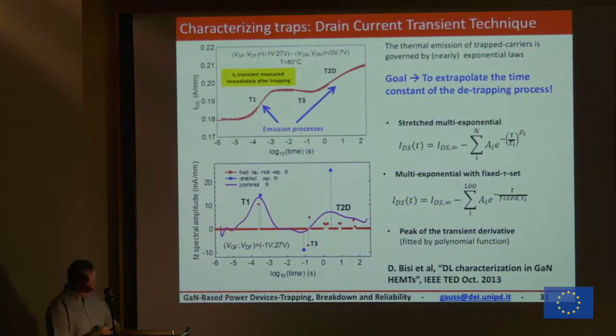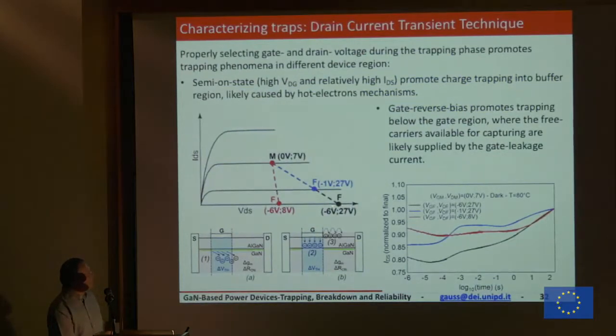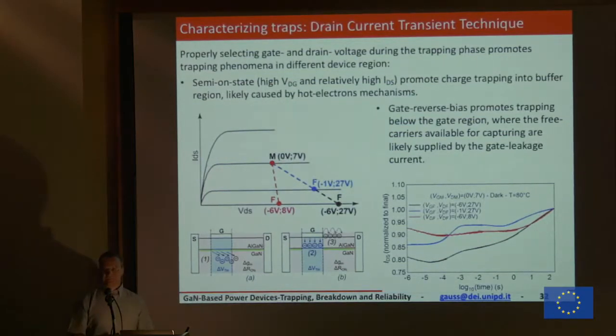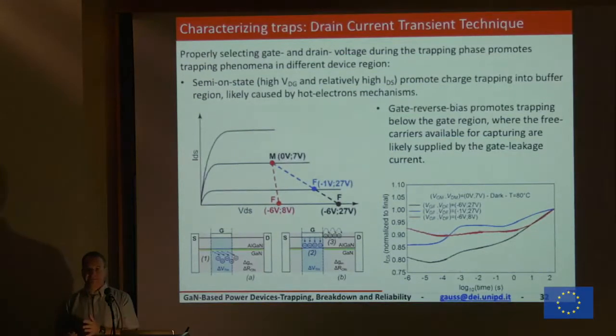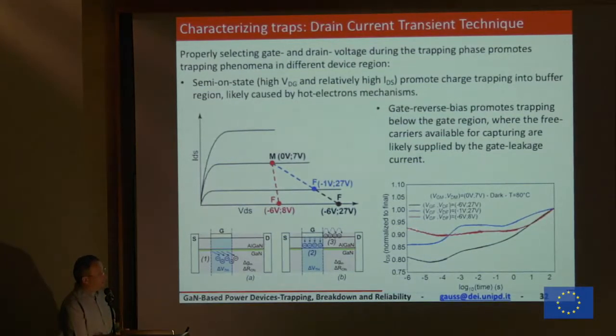Okay, first of all, let me tell you another thing. If we change the starting point, instead of starting from the F, we start from this black one, the blue or the red, these are the different transients. The blue one is what I just showed you, but we may have different transient conditions. So again, if we change the starting bias point during my measurements, I can really go to probe traps located in a different area. And maybe they are also different traps, because here I have a trap that is giving a lower current and then going up, and this dark as well. So again, changing the starting point, I can monitor different areas of my device, and I can probe different traps.